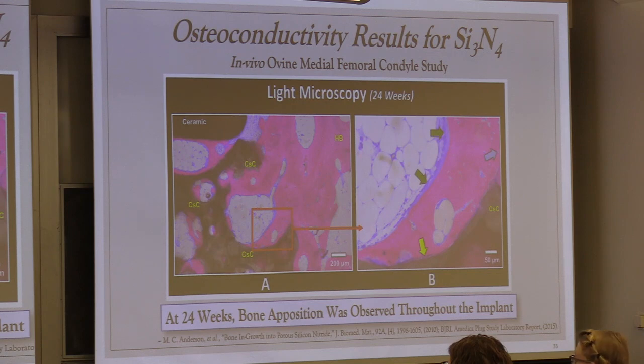And so the results were actually quite remarkable, and it showed that in this implant, bone had grown from both directions all the way through the implant by the 24-week endpoint, which was really fantastic to show that it really had great osteopromotive characteristics.